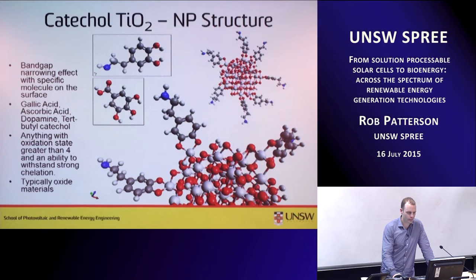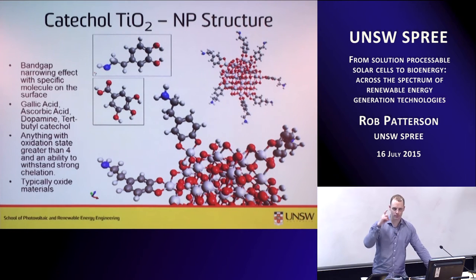And that's part of the motivation. So this is basically what it looks like. And so the reason why the science has been attributed to why the bandgap gets narrowed by these surface molecules is that there ends up being a strong surface dipole between the titania and the molecule, the ligand that's on the surface. What happens is an electron goes from the ligand down to the titania, and a hole jumps up onto the ligand. And that's kind of stuck there. So it ends up producing the strong surface dipole, which has the potential to lower the bandgap of the material.